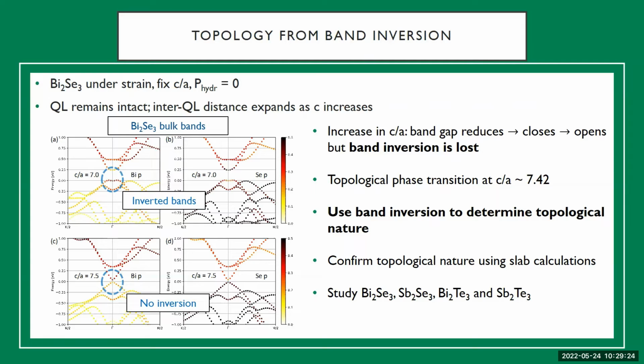And we used this band inversion as a signature of the topological nature of these materials. So in the figure on the left, in the top 2 panels, I show the band structure of these materials projected onto the bismuth p band and the selenium p band. In panel A, we can see that near the gamma point, which is at the center, the band just below 0 comes from bismuth p, and the band above 0 comes from the selenium p. Whereas if you apply considerable strain on the material, in the bottom panels C and D, the bismuth p is now above 0, and the selenium p is now below 0. So they've exchanged positions, and so the bottom panels C and D show a trivial system, whereas panels A and B show a topological system.